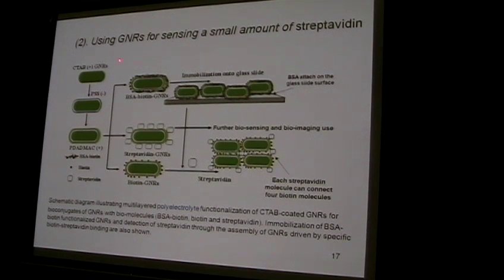Now here, the gold nanorods are synthesized chemically and have this CTAB on the surface. During the process they have a positive charge, and then we put in the PSS with negative charge, and then we put in another polymer with positive charge, with several layers coated.